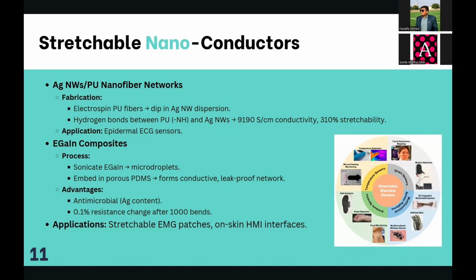Number one is antimicrobial. This is because of the silver content in it. Then secondly, the maintenance of the performance. Even after 1,000 bends, just a 0.1% resistance change is visible. The main application is ideal for EMG patches, tracking muscle activity, or on-skin human-machine interface. These conductors ensure that our wearable sensors stay reliable no matter how much we move.